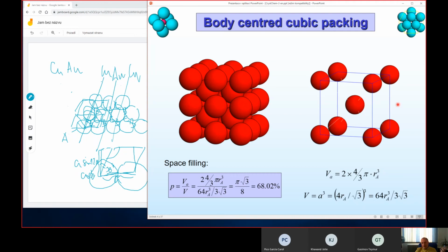But we have additional atoms here, which are at the distance of one lattice parameter, while the atoms in the corners are at the distance a times square root of 3 over 2, so 1/2 of the body diagonal, which is a closer distance compared to the other 6 atoms, which are in the centers of the neighboring unit cells.